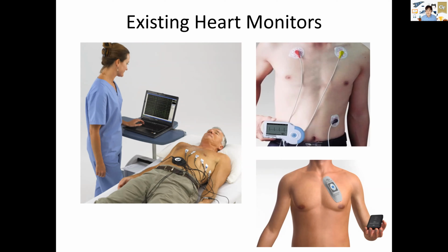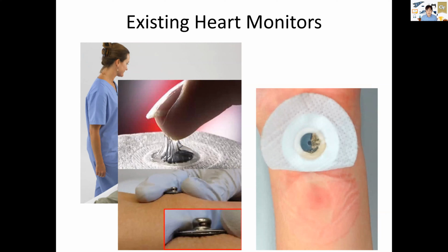So it's very heavy. So they had to use aggressive tape to mount this device to the skin and secure that contact. But more importantly, once you flip it over, when you look at the interface between the sensor and the skin, you see a bigger problem. Now the sensor is made of rigid metal, and our targeted skin is very soft. It has curvilinear features. That's why once you put this rigid sensor to the skin, there's an air gap, which is causing electric impedance issues.